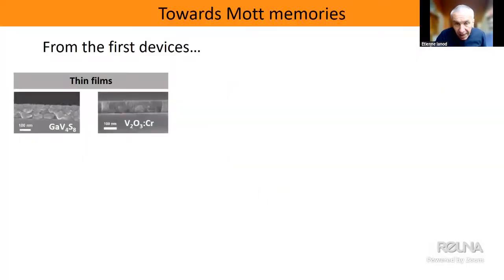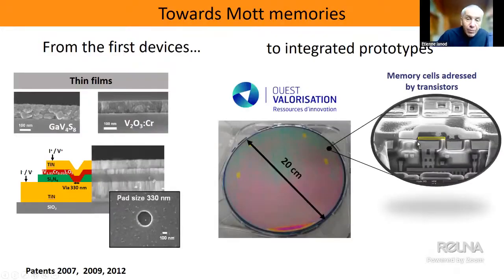But also one thing I would like to highlight, if we think about application, here you have a nice example. Our film, the thin film that we have deposited, in collaboration with CEA in France. You see, at the bottom you have a lot of complicated stuff like transistors and so on. The film is deposited on top of this, but then as you can see, it's covered by additional electrode, by many different layers on top of this. So it's nice because it's a strong protection against humidity or so, even if the material was a bit sensitive to moisture, air, aging in a way or another. In real devices, we can clearly see that it can be protected against this by covering by top electrode and so on. So this issue is not too serious, let's say.